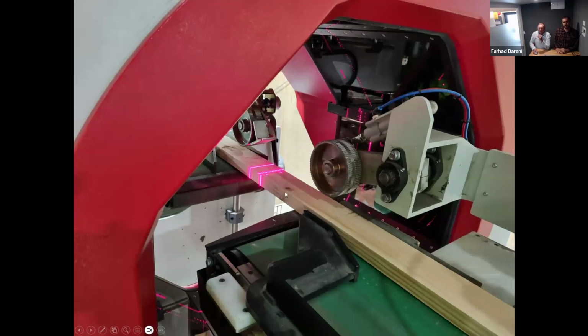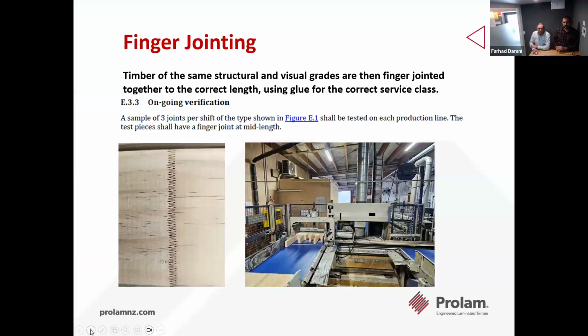And then this is our visual scanner. This straight line LED here is picking up the visual grading of the board, whereas this dot grader here is picking up the grain deviation. That's really important for our finger jointing, because we don't want the grain on an angle of more than 12 degrees for finger jointing, to keep the structural strength of our finger joint where it needs to be.